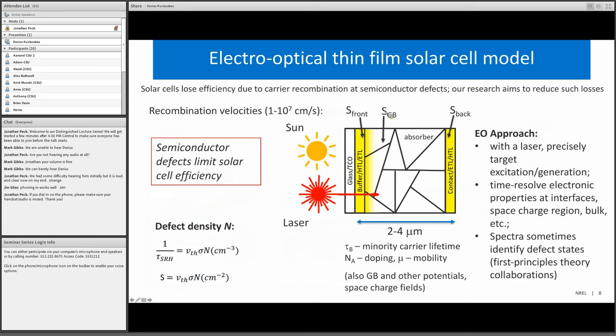Here is the more detailed description of the same cartoon. The interfaces, which include the front interface, the back interface, and the grain boundary interface, are described by recombination velocities. They're called velocities because they're measured in centimeters per second. These values can range from 1 to 10⁷. 10⁷ would be as fast as electrons are moving in a semiconductor. One would be the current passivation records, which are achieved in both gallium arsenide, II-VI semiconductors, and other materials.